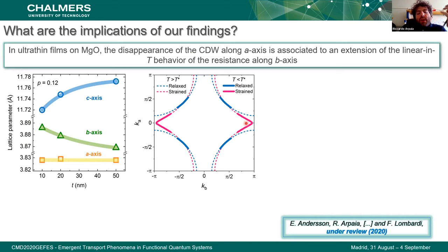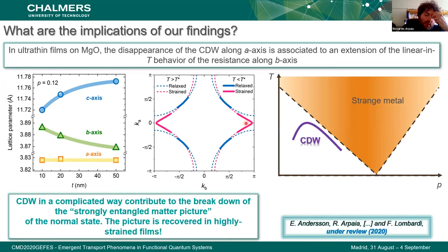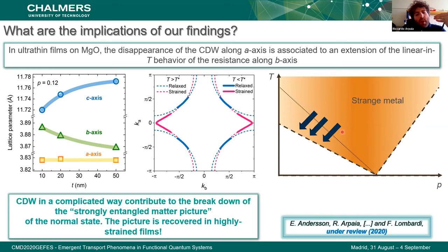So basically the picture that we have, supported by this experiment, is that the strange metal behavior that was expected in a very broad range of doping, even underdoped, is somehow blocked by the presence of the charge density wave. But as soon as we are able to remove the charge density wave, we recover the original picture in which this strange metal can also extend down to the underdoped region where the stronger correlations are present.